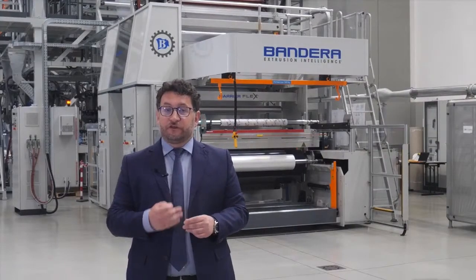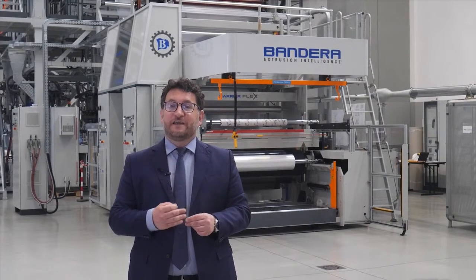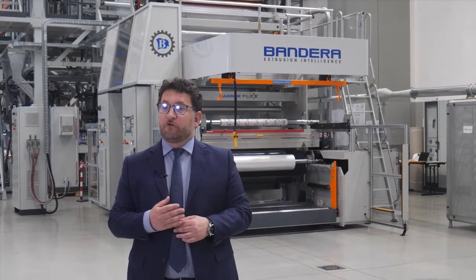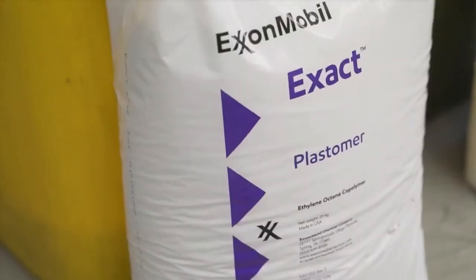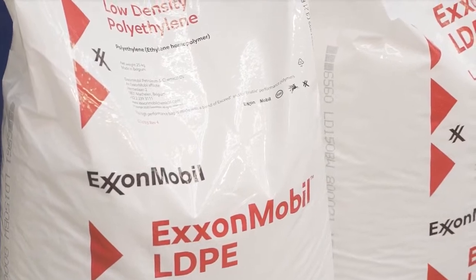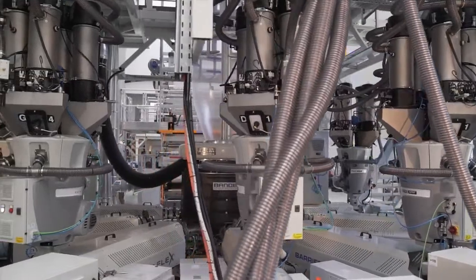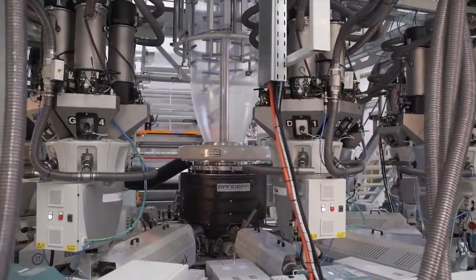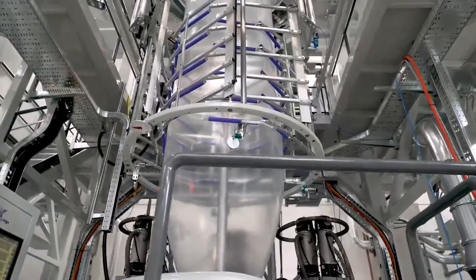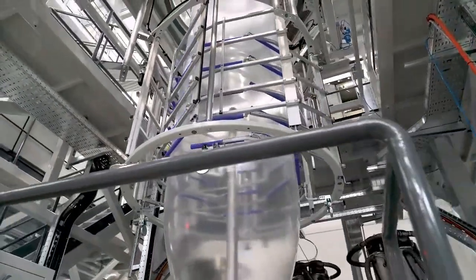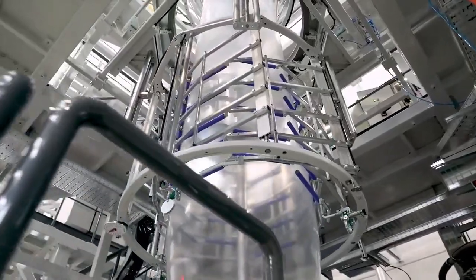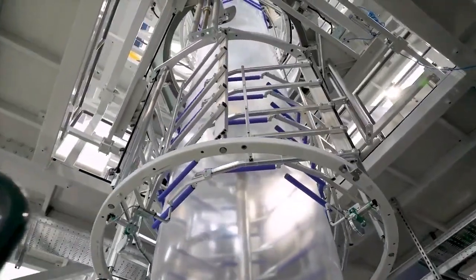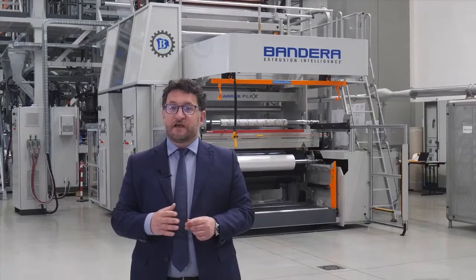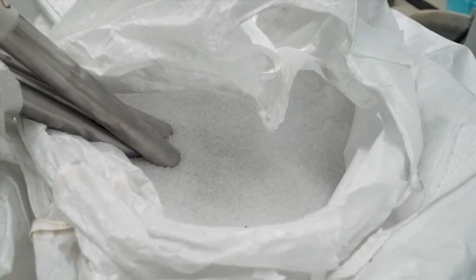The combination of these features allow us to get a granule which can easily and successfully process on a secondary blown film line. In particular, thanks to the fruitful cooperation with ExxonMobil and some of our top customers worldwide, Bandera is today capable to reuse the industrial wastes coming from a 7-layer EVOH barrier film production into a standard 3-layer blown film line to produce the sealant layer of a film used for stand-up pouches to pack detergent products or for mailing bags application. Both these products have been processed containing up to 50% of post-industrial recycled material.